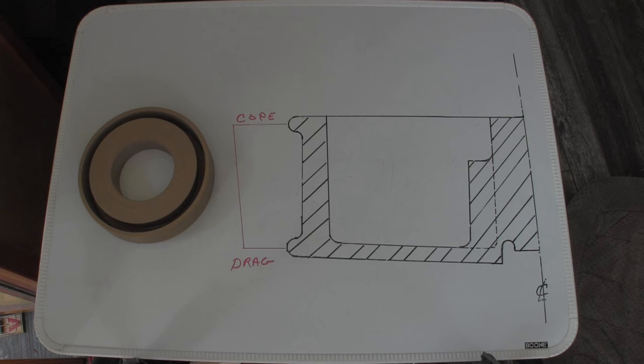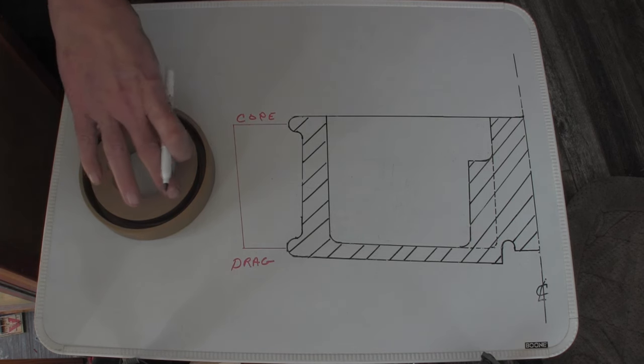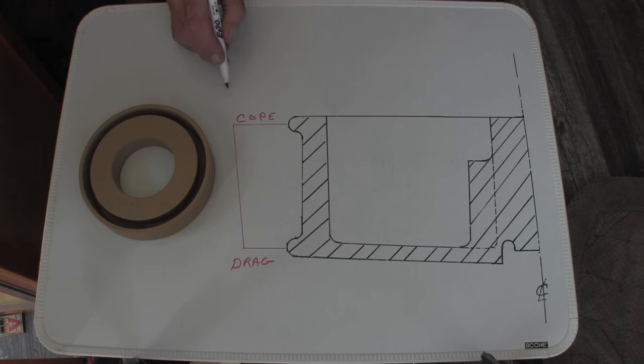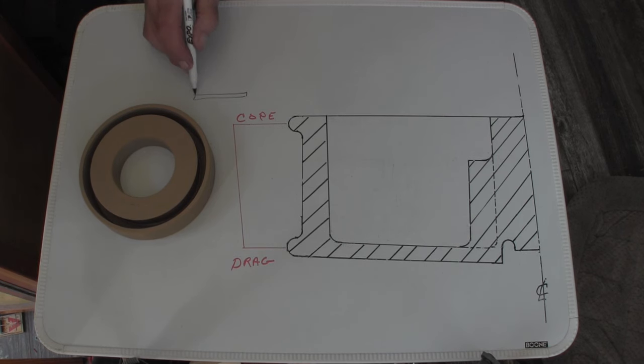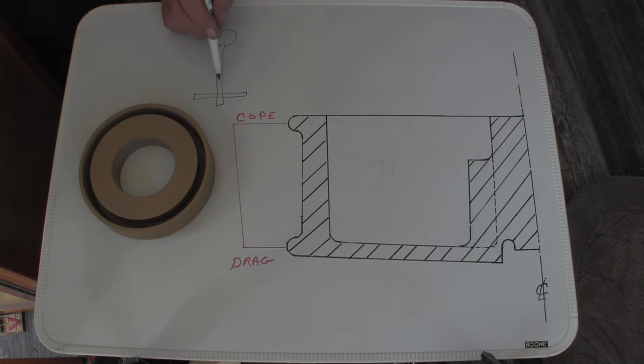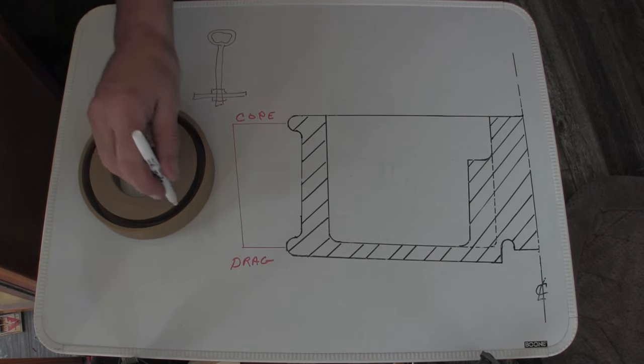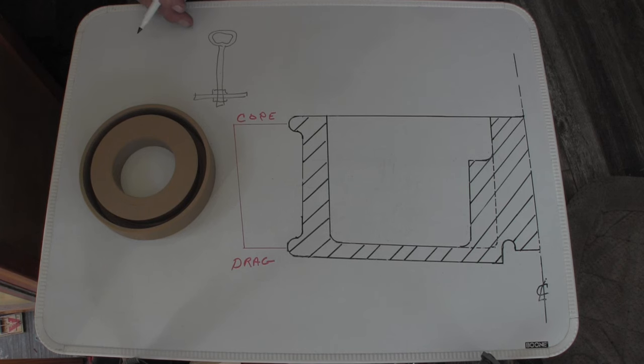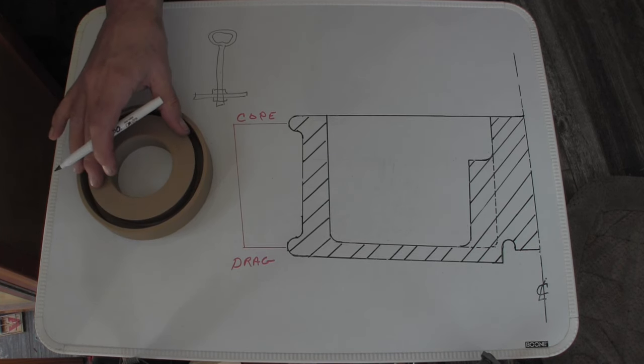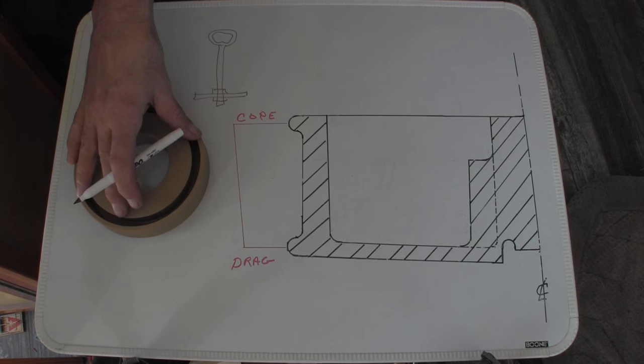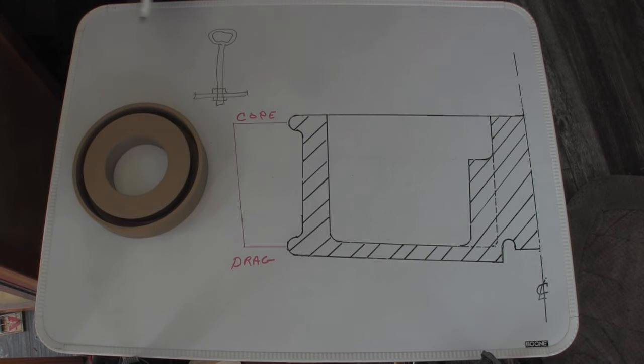Didn't look like a huge casting or pattern. To get this out, you could put three drawbars in here. A drawbar is nothing more than you put a washer here. You have a bolt coming up to an eye bolt here. Nut either side to lock it in place. And put it about three places, maybe four, around the core. Lift the core out in a way that you basically pick the core up and you can set it right directly in the mold. Unless you got to do something to it.